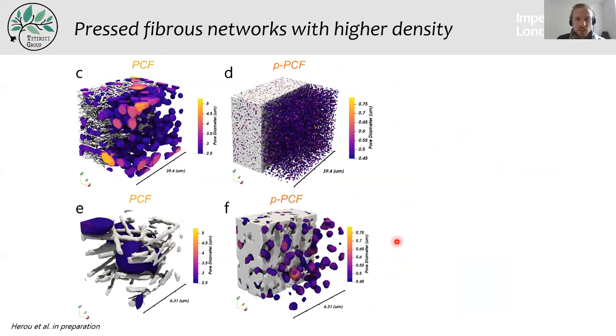And here are the results of the tomography, where we can see the unpressed sample here with a scale of 40 micron, and here a scale of 6 micron, where we can see the fiber shapes. And in color are the size of the pores from 2.5 to 5 microns. And here the pressed sample, because all the fibers merged together, we can't distinguish any fibrous shape anymore, but we just see that the size of these pores has been lowered by a factor at least 5 to 10.